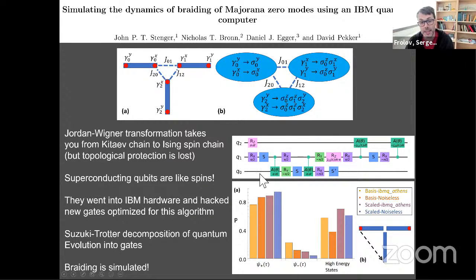Why did we need to change the gate set? That's because the middle site for this braiding operation is a coupling of 3 sites. And to do the quantum dynamics of that 3-way process, you need a lot of CNOT gates. And the CNOT gates are very costly. Each CNOT gate comes with a 1% error in a current quantum computer at IBM. So you can only have like 25 of them before you get a random outcome of your computation.